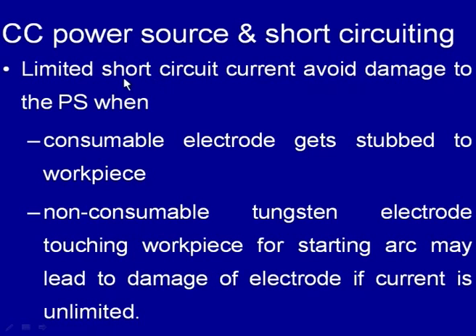In both cases, short circuiting can be damaging to the power source if a very heavy flow of current starts through the coils of the power source. In the case of constant current power sources, a limited short circuit current is achieved, and this limited short circuit current helps to avoid any kind of damage to the power source. This is a very good feature of the constant current type of power sources.